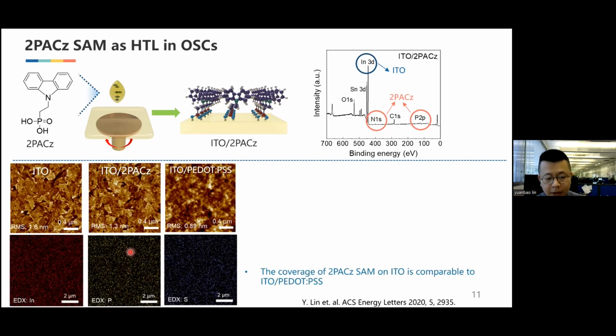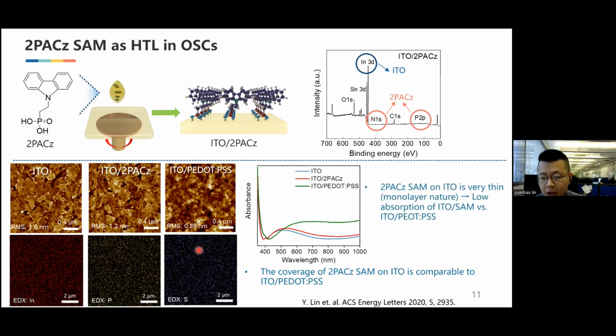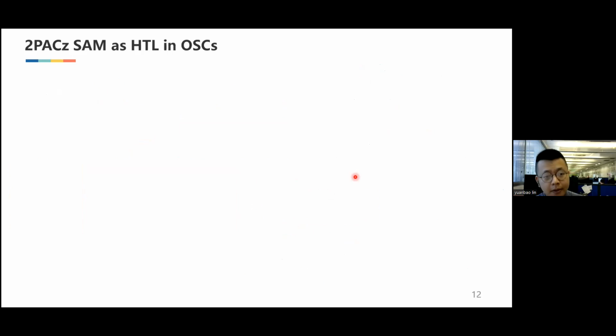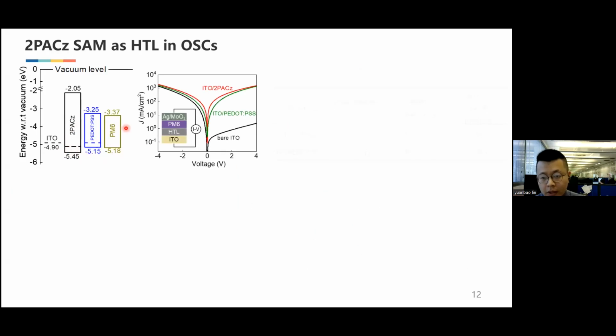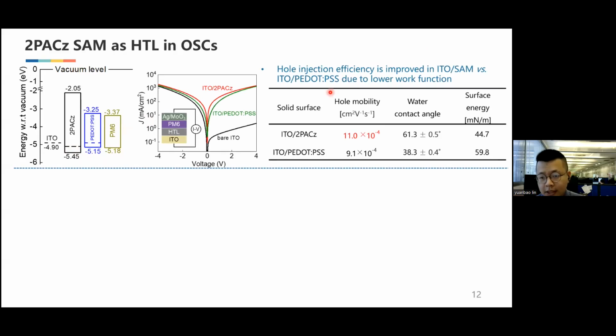But from EDS mapping, you can see the distribution of the 2PACz is very homogeneous as compared to the ITO and PEDOT:PSS. And also from absorption, the 2PACz absorbs less light as compared to PEDOT:PSS after 500 nanometers, which will benefit the photoactive layer. And from the energy level, because this 2PACz has a work function of around 5.3, which will increase the hole extraction efficiency.